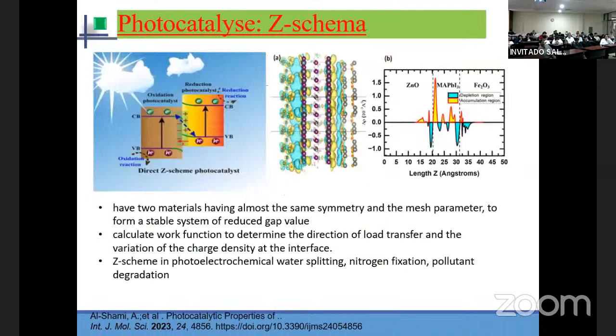The second solution is the heterostructure. There are many papers that treat this case. So we are looking for two materials having almost the same symmetry and the same lattice parameter, and we can also compute the work function to know in which direction the electron can move, from which semiconductor to the other. Also, we can compute the charge density at the surface of this material, and we can see the electrostatic potential in this state. So the Z-scheme for this application is applied. It is applied for different applications like water splitting and degradation of pollutants.